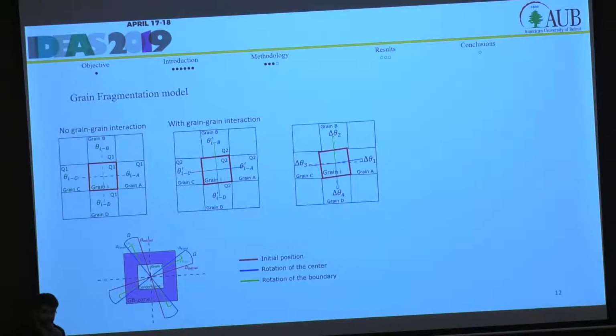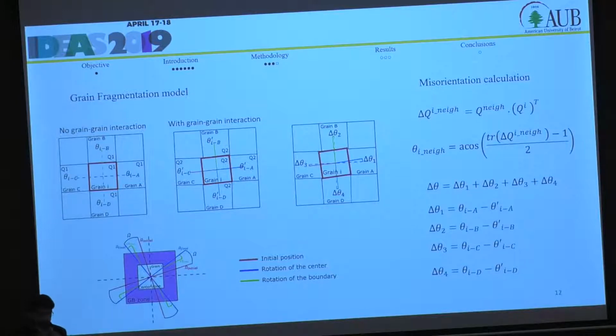First of all, we took 2 calculation steps. In the first one, we have no grain-grain interaction. That means the GND effect is not accounted for, while for the second one, we account for the geometrically necessary dislocation effect. So in each case, we calculated the misorientation angle between neighboring grains, and the difference between them is our misorientation angle that will decide whether the fragmentation will occur or not.